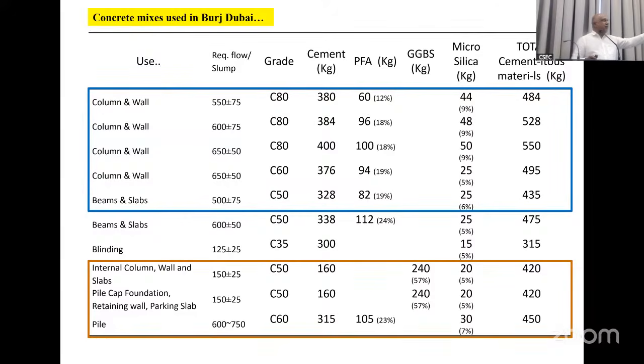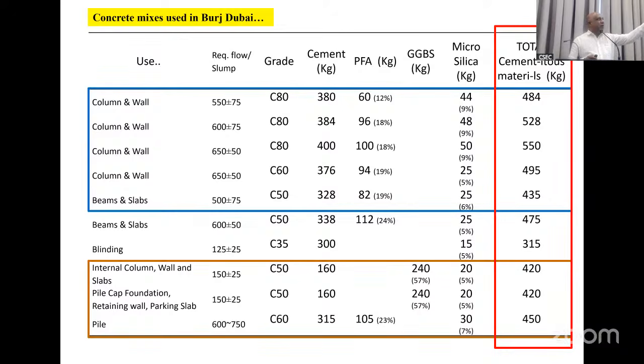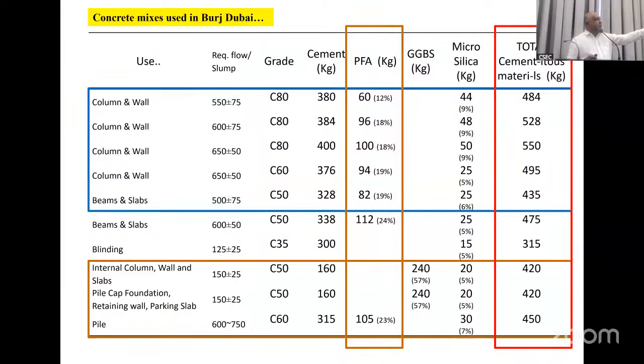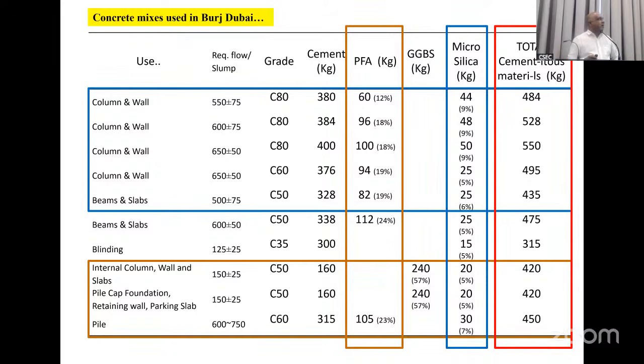So this is the complete design which was used for Burj Khalifa. As I mentioned, you see total cementitious material, not only cement, but cement plus all other materials. Total cementitious material is less than 550. Wherever we use above 550, of course there won't be any issues nearby, but it will not last. So that's why you need to reduce it. You can see fly ash is between 10 to 24%, and microsilica 5 to 9%. These are the things we need to keep in mind, just as a thumb rule. As engineers, we should know where these values are moving.